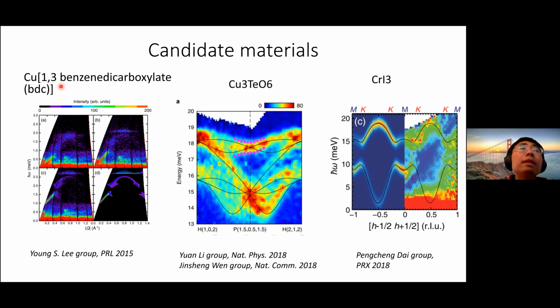In other words, same as the Dirac point in graphene. At a zone corner momentum, Dzyaloshinskii-Moriya interaction can open up a gap and drive the band into a non-trivial topology. In particular, the non-trivial topological bands can give rise to chiral edge states on the surface of the system. This is what people have concluded based on this inelastic neutron scattering study.